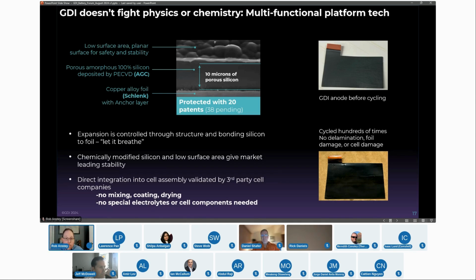So what do you have? You got a sponge. Now when it absorbs lithium, first it fills in all those pores, then it starts to expand. And what that does is it has a very small delta per layer. Our anodes actually only expand between 10 and 15 microns per side, depending on your loading and how hard you're running the silicon. That's less than the thickness of a human hair.